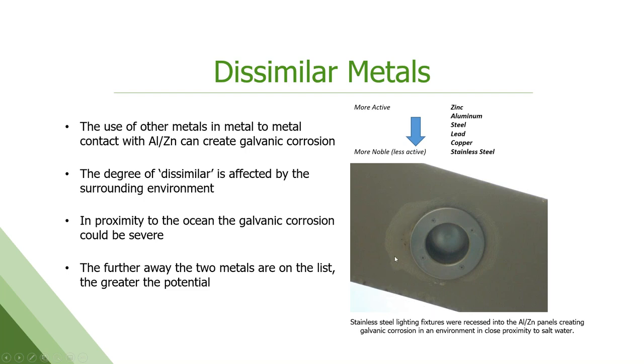What's happening, it looks like the paint's bubbling up, but what's happening is the zincalume, galvalume underneath is corroding away. So there's nothing left for the paint to stick to, which is why these claims almost always come in as, my paint is failing. Well, the paint's failing because the substrate's failing. But what you see is the paint failure first.